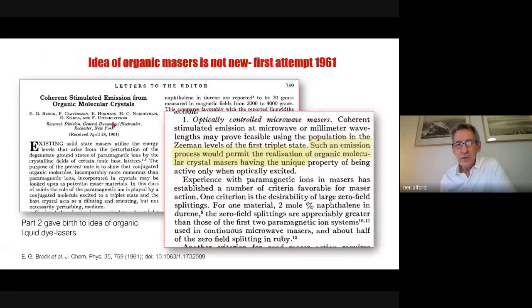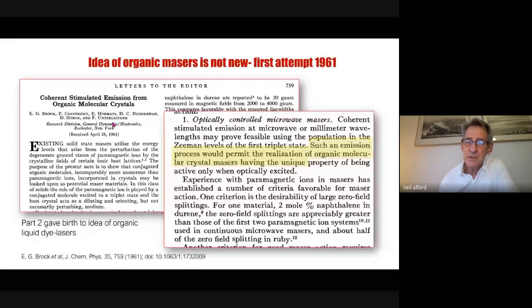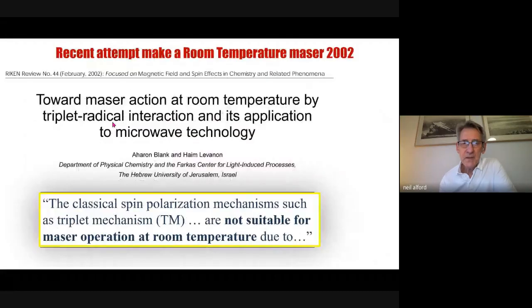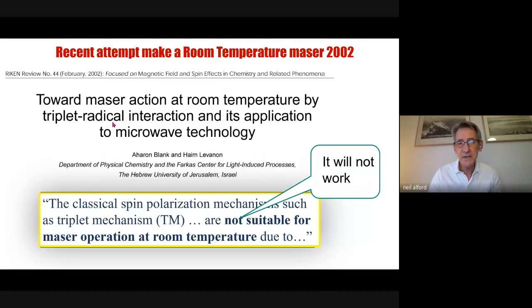Now, the idea of organic masers is not new. The first attempt to do this was in 1961. And then the most recent attempt, before we did the maser, was in 2002 by Aaron Blank and colleagues at the Hebrew University of Jerusalem. And what they said within this paper was that the classical spin polarization mechanisms, such as the triplet mechanism, are not suitable for maser operation at room temperature. In other words, it wouldn't work at room temperature.